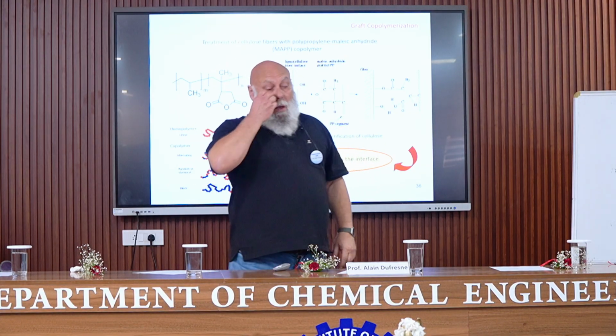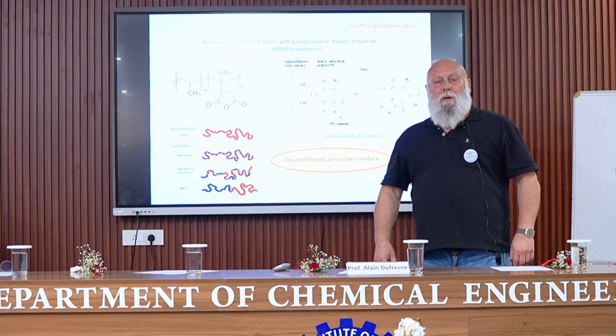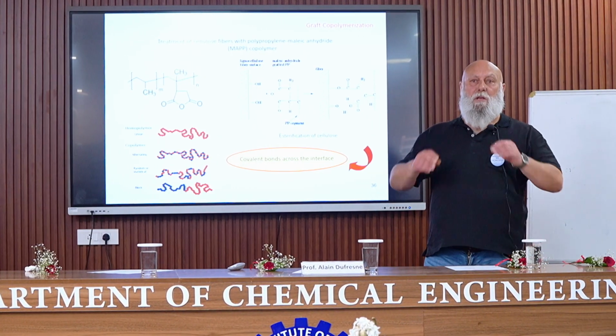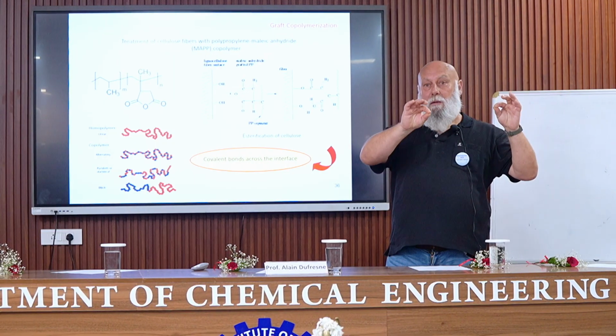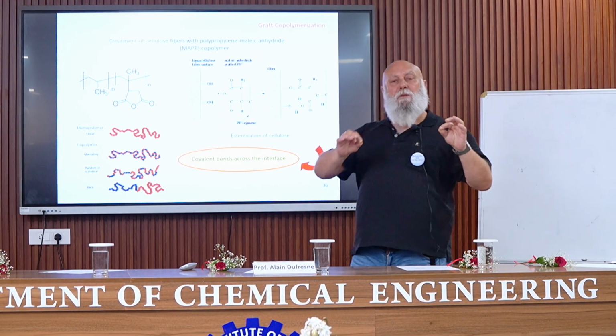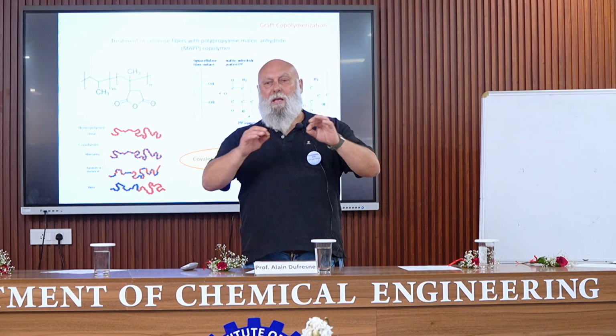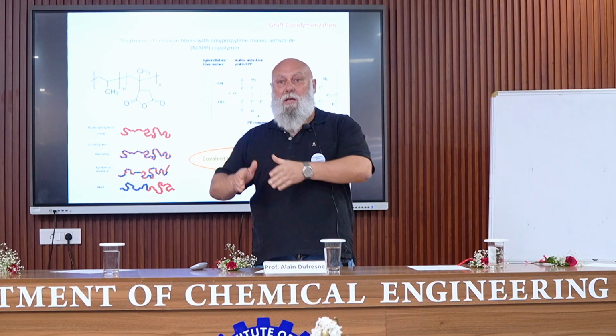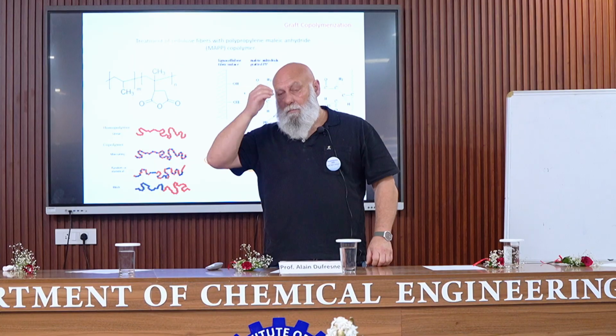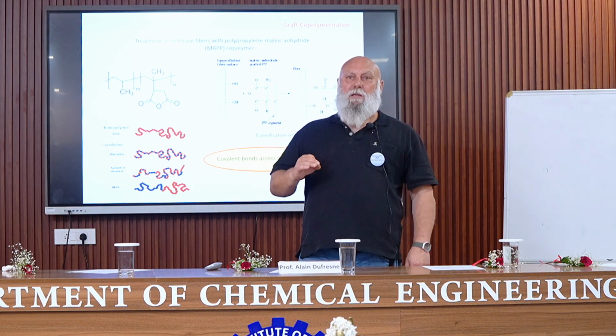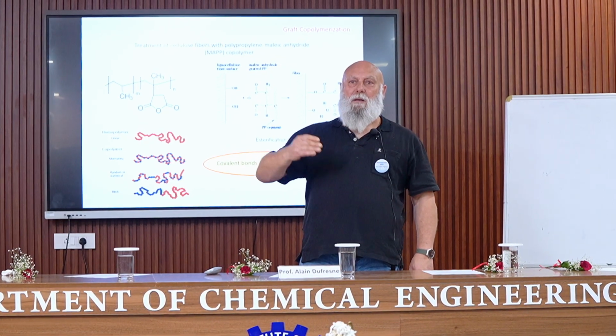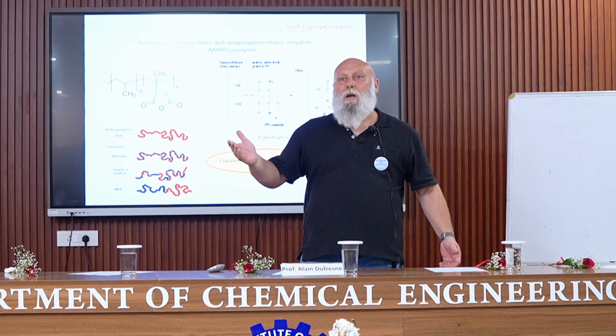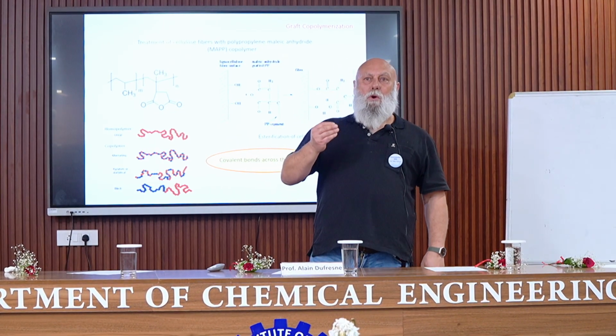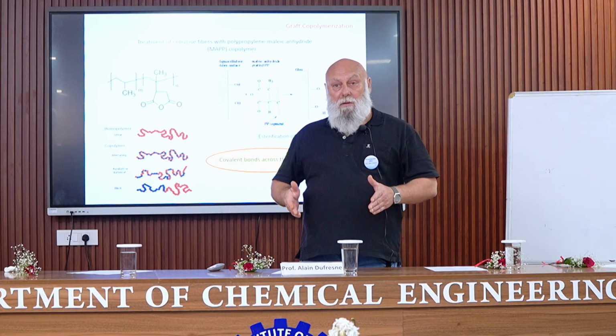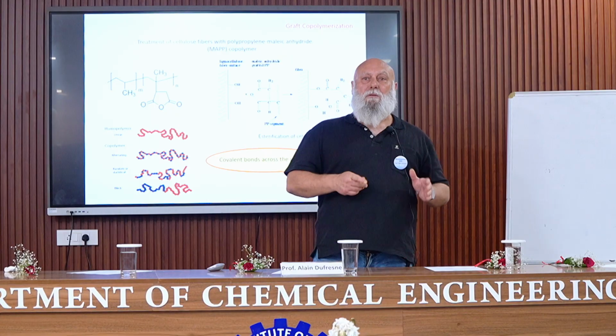Yes, exactly. One important parameter that I will mention later is the aspect ratio of the fiber. The aspect ratio is the ratio of the length divided by the diameter. This is important. To have an efficient reinforcing effect, it's necessary to have an aspect ratio which is higher than a critical value. When considering particulate or fillers, which can be more or less spherical particles, or platelet-like particles, this aspect ratio is very low, meaning that we can only expect a low reinforcing effect.